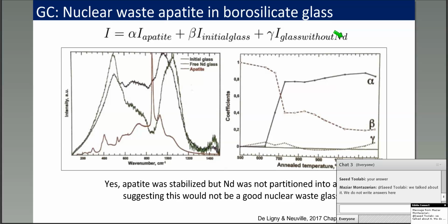So where that applies to your question is that even though they didn't have a signature from the glass, let's say, specifically associated with this sub mole percent neodymium, they do see a large change in the spectra of the glass itself. And so what the limit of that resolution is, I don't honestly know. But depending on the elements, particularly if you're talking about rare earth elements, there are some pretty strong changes in the spectral features that you can see. For example, in our lab, we've done dopants of rare earth elements down to 0.1%. And you can see a peak coming from those dopants at 1%.